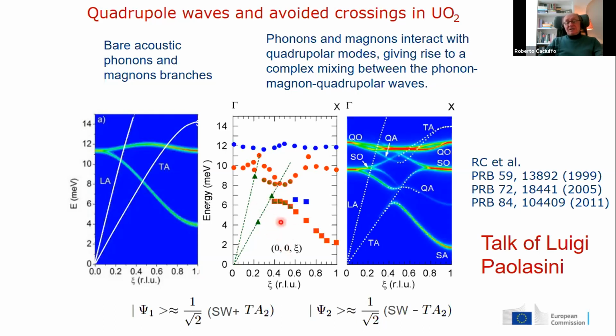For instance, here is the anti-crossing between a transversal acoustic phonon and the acoustic spin wave branch. What happens at the anti-crossing positions is that the mode is a linear combination of magnetic and phonon modes. Neutron experiments are performed at low temperature with small momentum transfer, and in this condition, it is difficult to observe the phonon contribution. So this is essentially a map of the magnetic part of the mixed excitations. On the other hand, with inelastic X-ray scattering, you measure directly only the phonon part, and then you can have access to the complementary mixing information in this scenario.